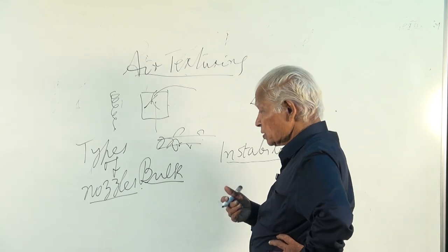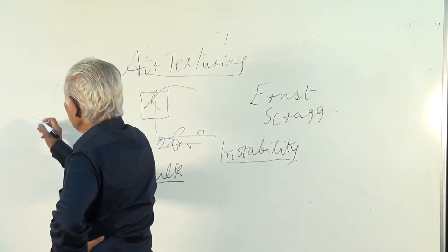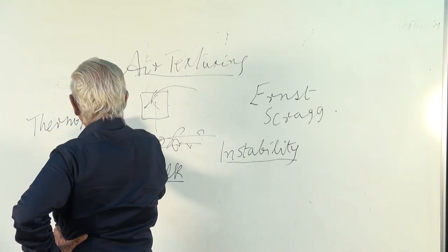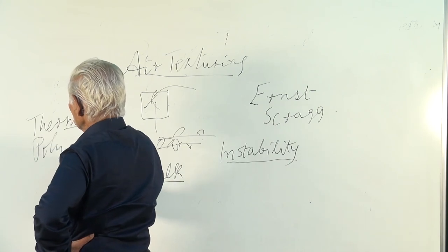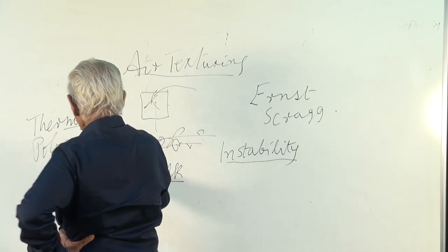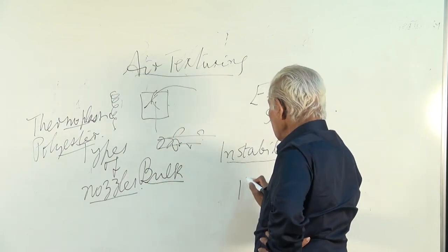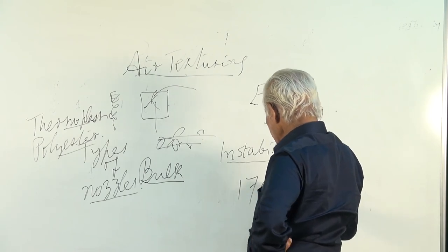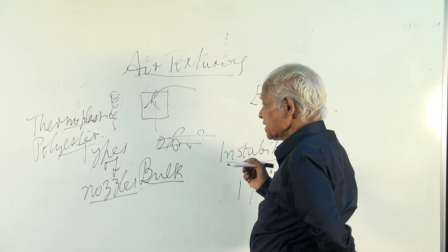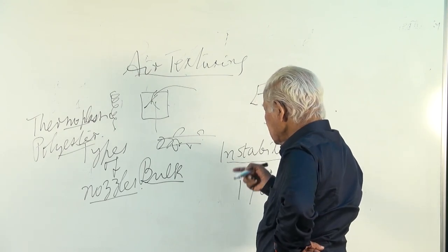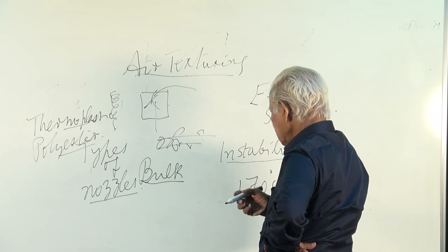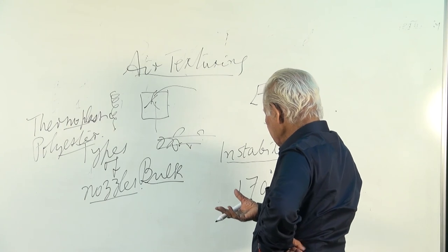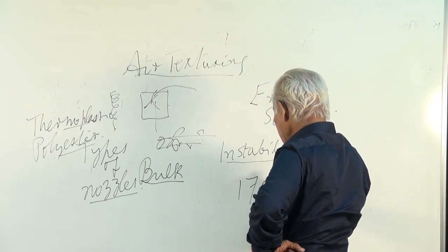And a thermoplastic fiber such as polyester is heated at a temperature of 170 degrees in the presence of the twist, and then cooled and then detwisted. The detwisting takes place in the draw texturing machine by some of these false twisting devices, or by other types of twisters.